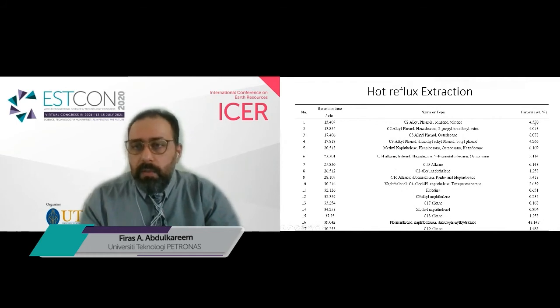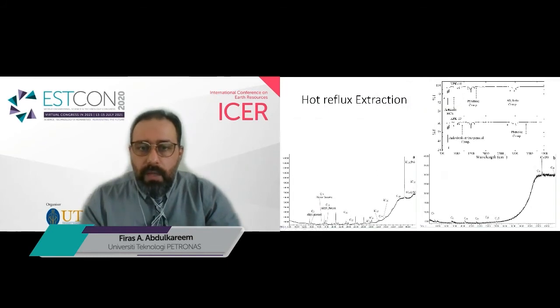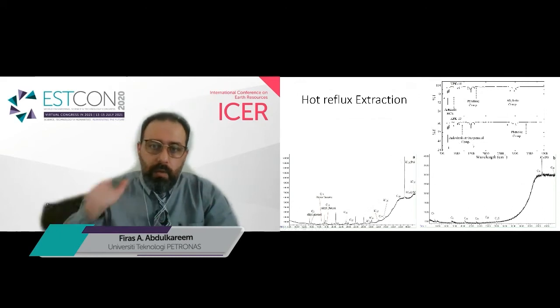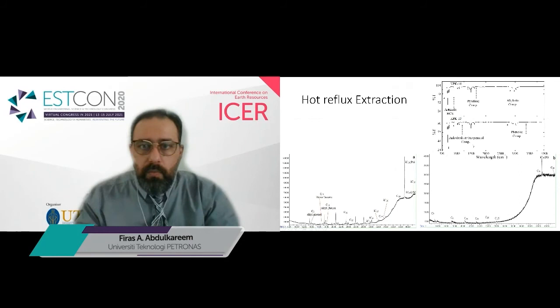So for the hot reflux extraction material, we can see that the extracted matter, or the residual oil retrieved from the process, can range from C5 up to C20, with a different type and range of hydrocarbons extracted. On the other hand, as we can see here for the hot reflux of both samples, they also represent some anhydrides and oxygenated compounds, with some addition of aromatic and aliphatic compounds and components extracted.